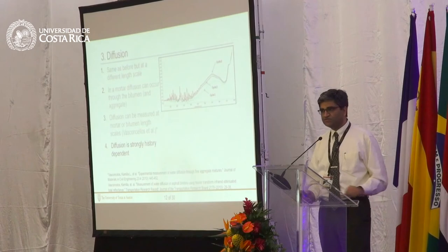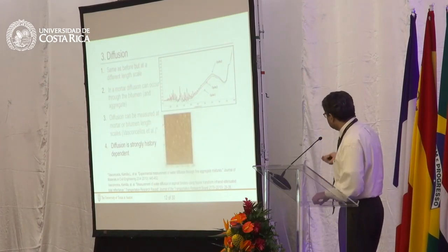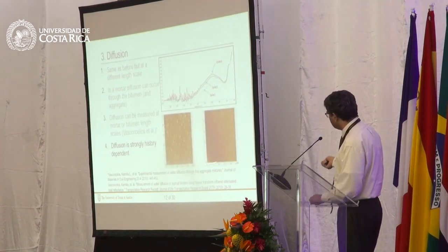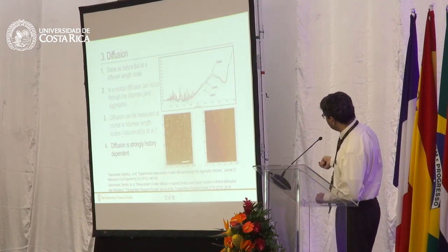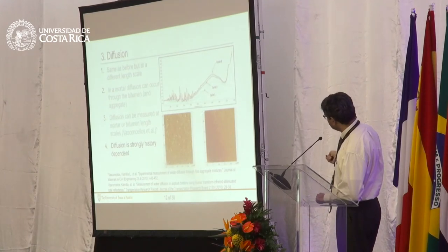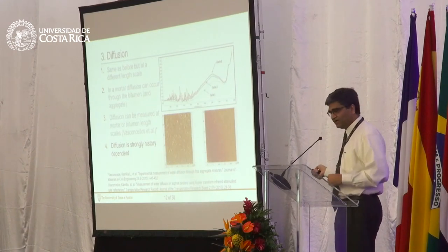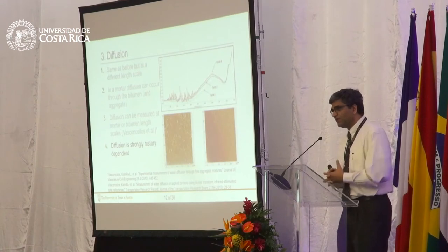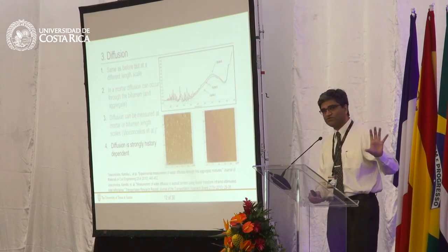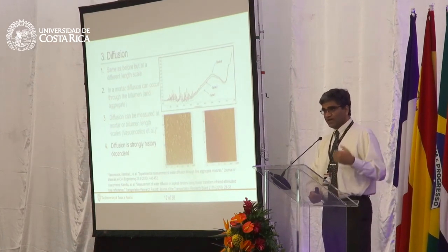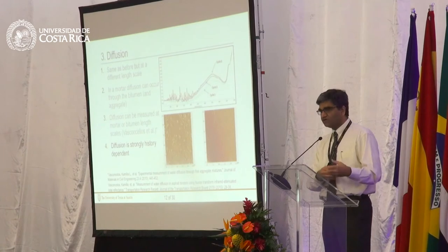It is permanently changed. In fact, this is a very old study, about 6 or 7 years ago, where we used atomic force microscopy. I don't know with this light if it's clear or not, but you can see this was the structure of the original bitumen. This was the structure of the same bitumen under the same condition, except that it was exposed to water and dried. So there was permanent change in the structure of the bitumen. Meaning you don't have to constantly expose the bitumen to water for months together to wait for moisture damage to occur. Every time you expose and you remove water, there's some change that is cumulative and it adds on.